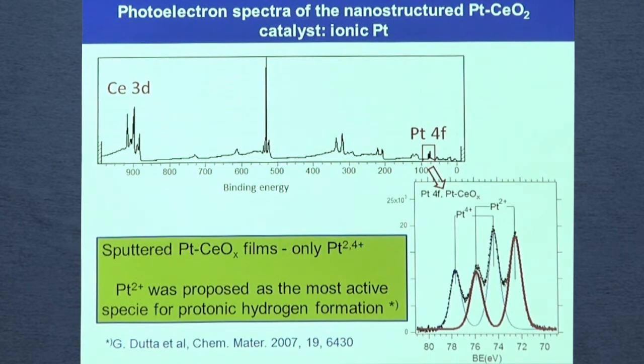Well, now, the question is what kind of material we are using. If we check by XPS, by photoelectron spectroscopy, we can see that the platinum is not metallic. Platinum, after deposition, is ionic, in the platinum 4+ and platinum 2+ state. There is no metallic platinum.